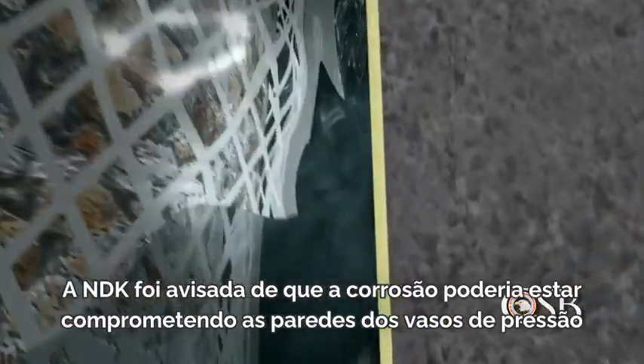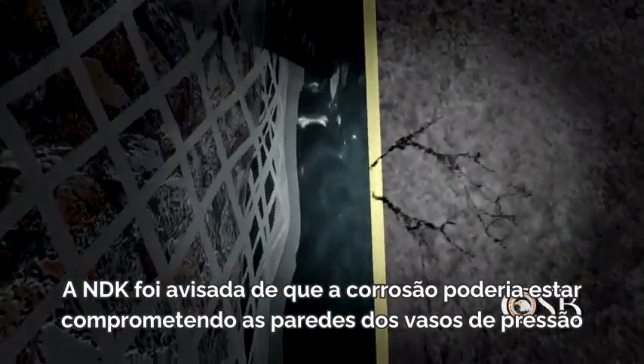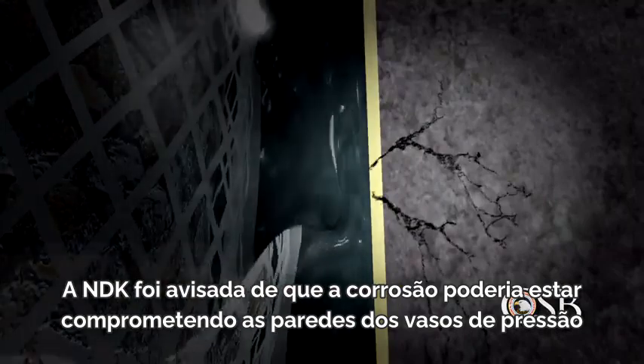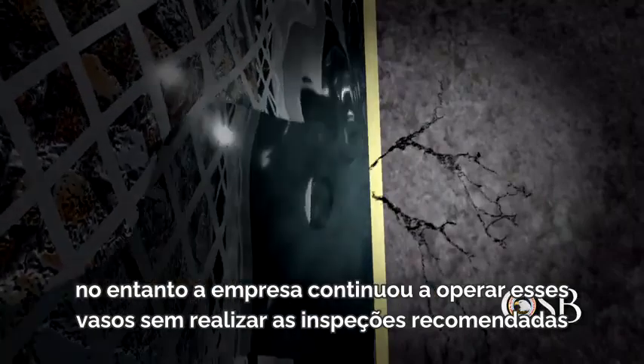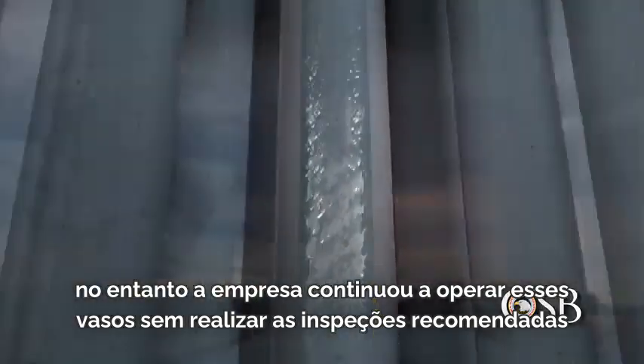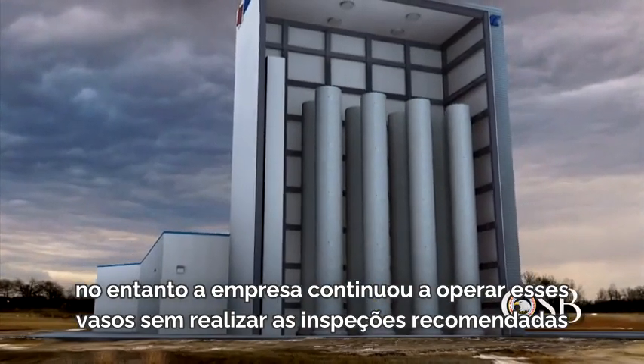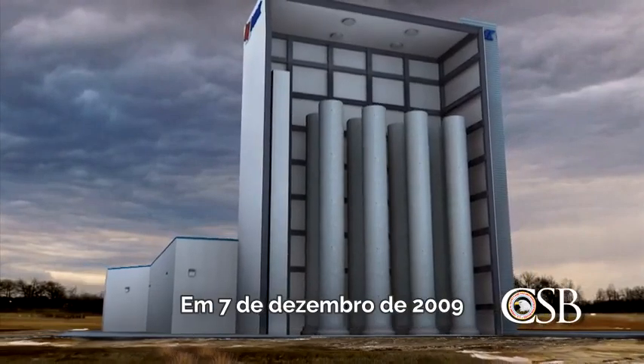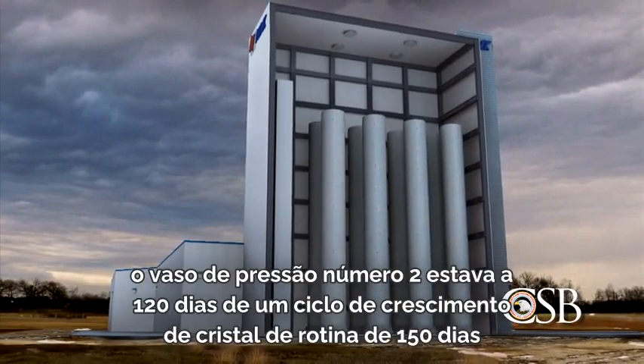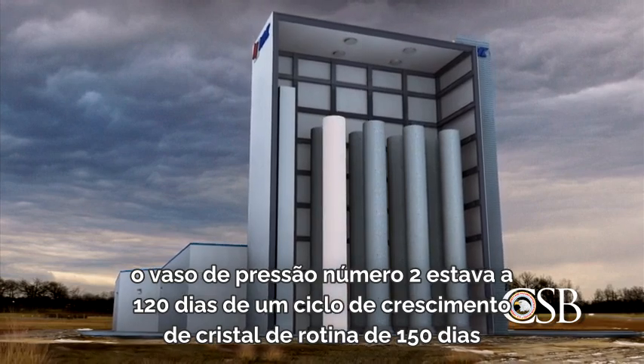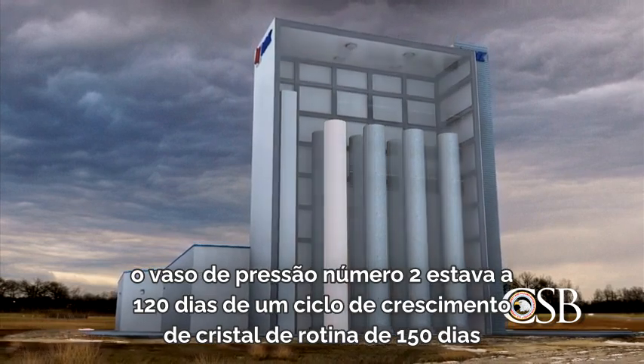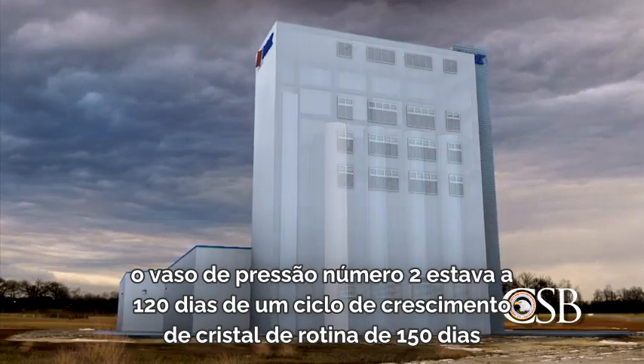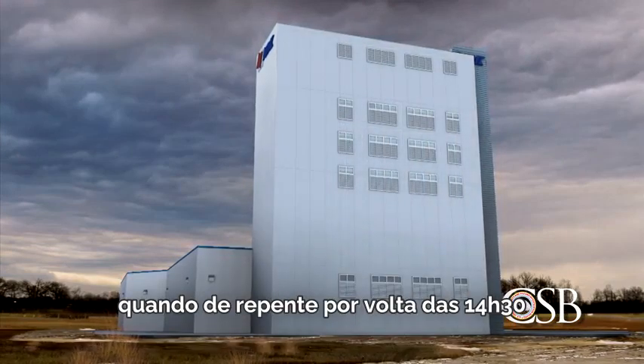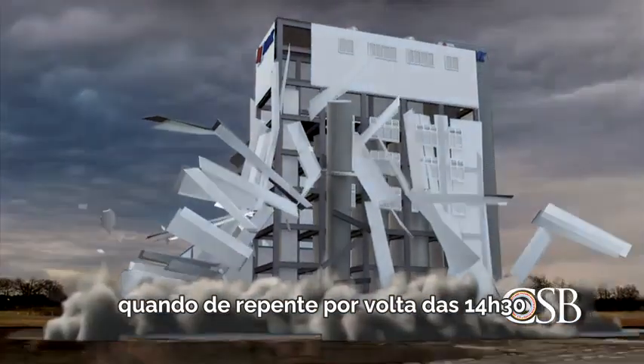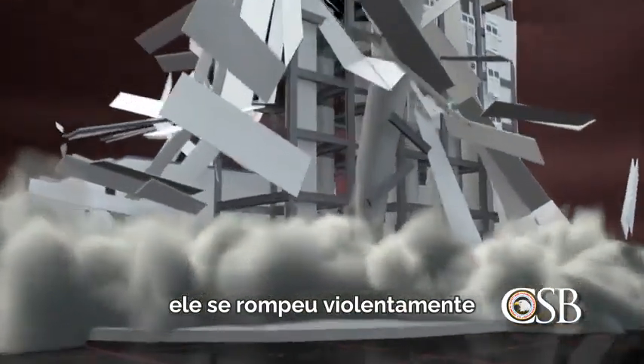Over the years, NDK was warned that corrosion might be compromising the walls of the pressure vessels. Yet the company continued to operate these vessels without performing recommended inspections. On December 7, 2009, pressure vessel number 2 was 120 days into a routine 150-day crystal growing cycle, when suddenly, at about 2:30 p.m., it violently ruptured.